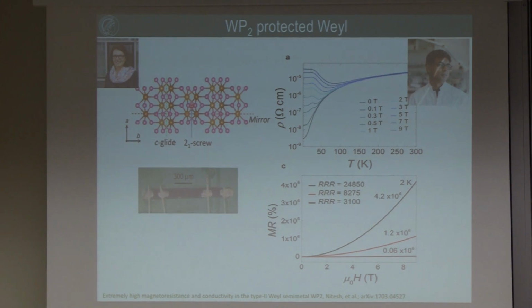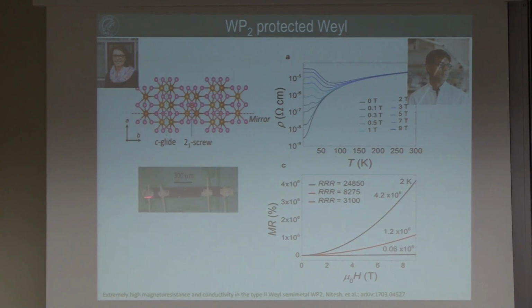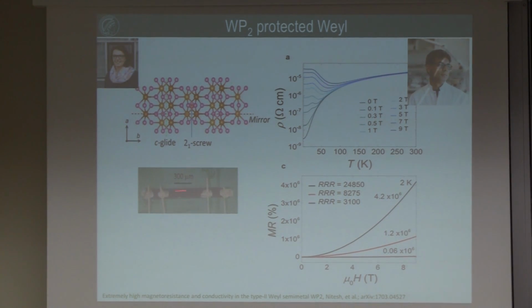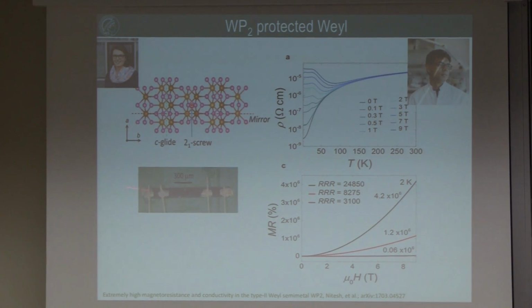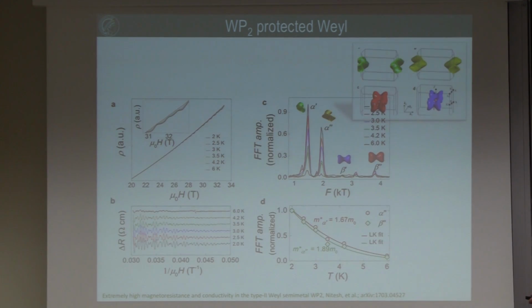So then we thought, okay, this might be a system for hydrodynamics. And the nice thing here is, because this is this very needle-type crystal structure, we could easily make wires out of this material without using a FIB. So we avoided accidentally getting gallium doping in this material.